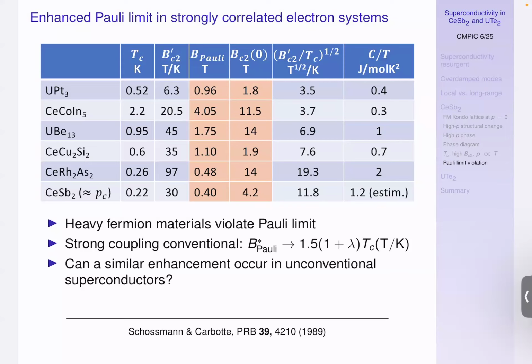A lot of heavy fermion superconductors, we always have the Pauli limit calculated by the standard rule of thumb, and that's compared to the actual upper critical field. And a lot of cerium-based superconductors, and even to the side the uranium-based ones, which are always a little bit suspicious, but a lot of the cerium-based ones break the Pauli limit by a long way. And so we jump to the conclusion, well, it must obviously be triplet, but is that really warranted? Because advanced calculations on conventional superconductors suggest the Pauli limit is much more subtle than just this rule of thumb. So before we jump to the conclusion of a triplet superconductor, let's see whether we can understand the Pauli limit for a singlet superconductor. Your argument was that the density of states seen by the susceptibility wasn't enhanced.